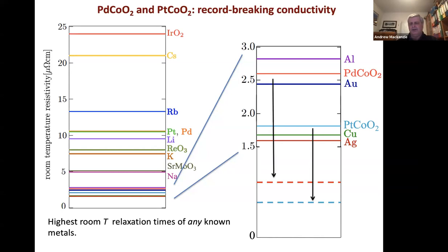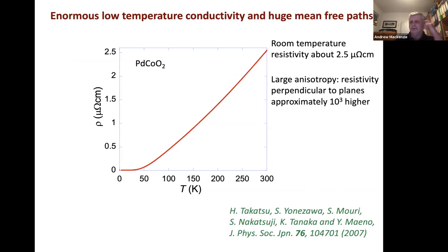And if somebody had told you 50 years ago, or now 51 years ago, that a triangular lattice layered oxide would be the metal that ended up holding that kind of record characteristic, you wouldn't have believed them. So the room temperature resistivity is already extremely low. They're incidentally very strongly anisotropic, as you could see from the Fermi surface. And the resistivity is about 1,000 times higher along the C-axis than it is in the planes.